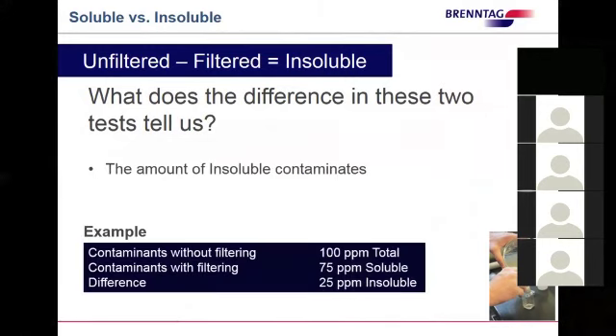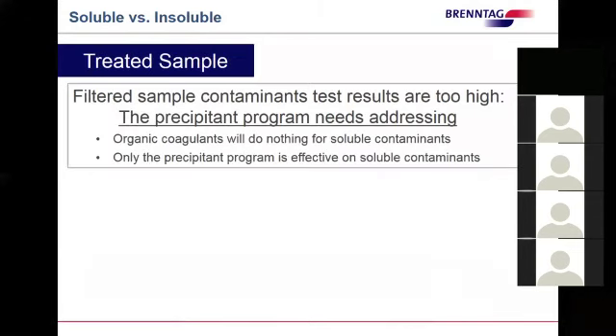Here at the bottom, there's just a really simple example. So if your contaminants without filtering is 100 ppm total, your contaminants with filtering are 75 ppm soluble, and then the difference is that 25 ppm that's insoluble. So simply put, once the sample is filtered, you can better determine where to start in product selection for your testing protocol. Certain coagulants address soluble contaminants better than others. So it can be a time saver and lead to a much more effective treatment program. It's really a deliberate approach to a process that is all too often hit or miss, or a bit like throwing darts.